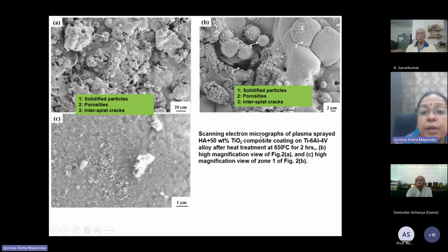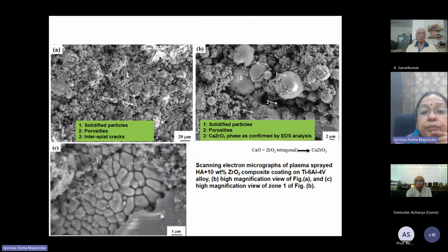And this is the plasma sprayed hydroxyapatite composite coating on Ti6Al4V after heat treatment. After heat treatment we saw a little bit of crystallization of the coating. There was also a little grain growth, and a stress relieving operation. The other coating was highly stressed, but whenever we did the heating operation, the stress was completely relieved. That was one of the interesting features of this heat treatment.